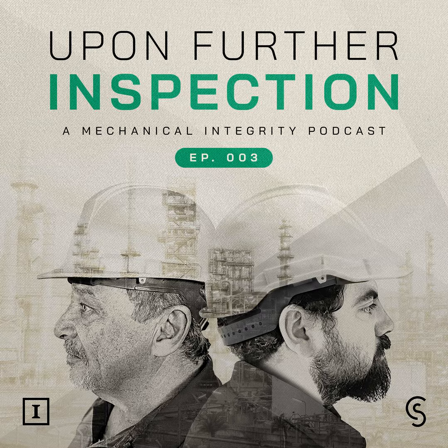In fact, on PSA vessels, they try to avoid welds as much as possible. And back in the day, we used to have manways on PSA vessels. 15 years ago, 20 years ago, they quit putting manways on them to reduce the stress risers. And they just put an oversized top head center nozzle on them so that when you went inside, you could go through there instead of having a separate manway on the sidewall. Yeah, because the fatigue would be way too much. Yeah, it's like eliminate stress risers as much as possible.